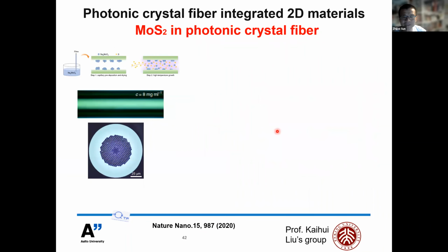For nonlinear optics, the group also demonstrated growing MoS2 inside of the photonic crystal fibers. This is their growth strategy. And this is what the as-grown photonic crystal fiber looks like. You can see it is very uniform. This is very, very suitable for nonlinear optics because the uniformity will give us much less scattering loss.